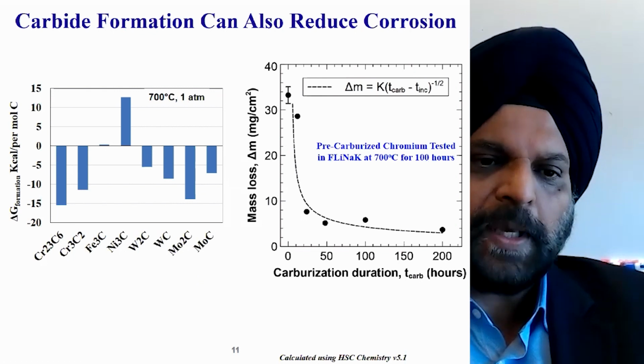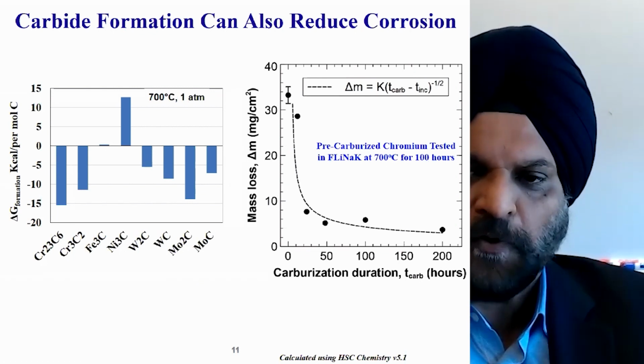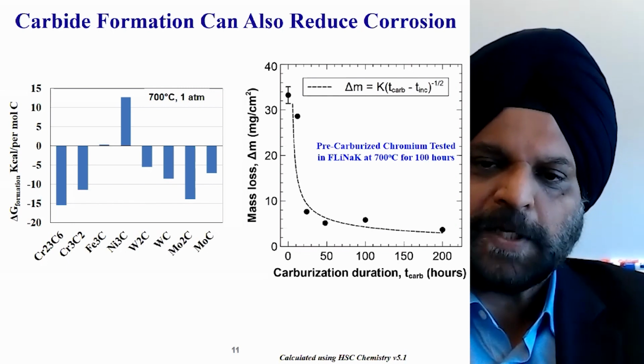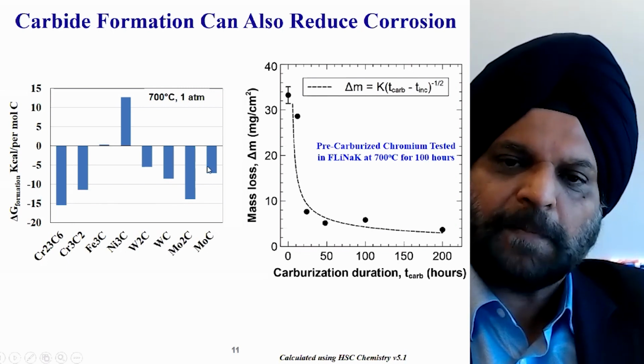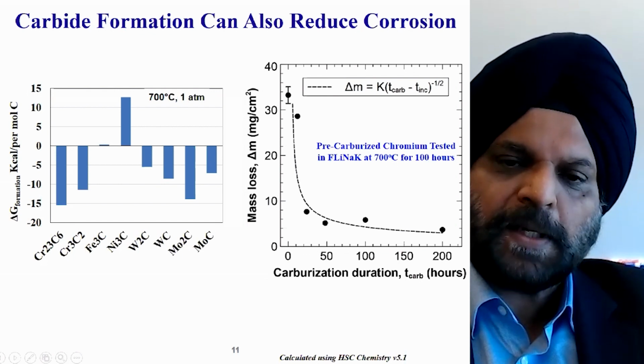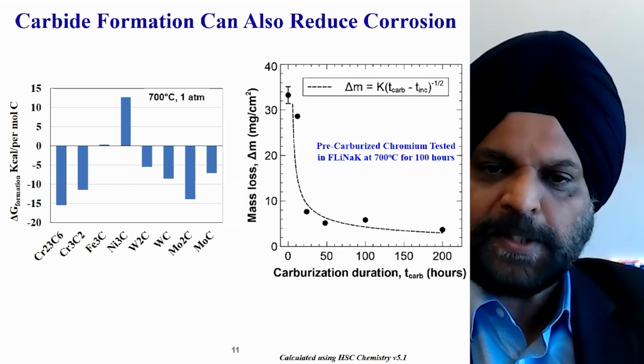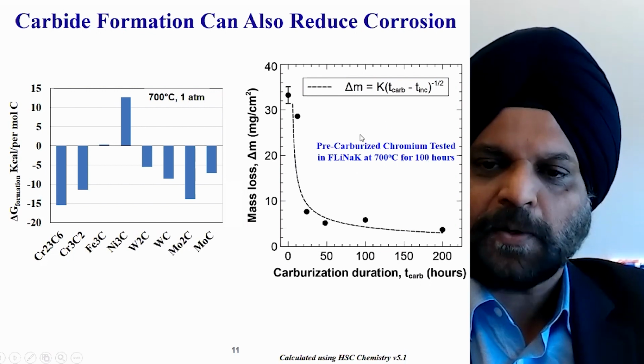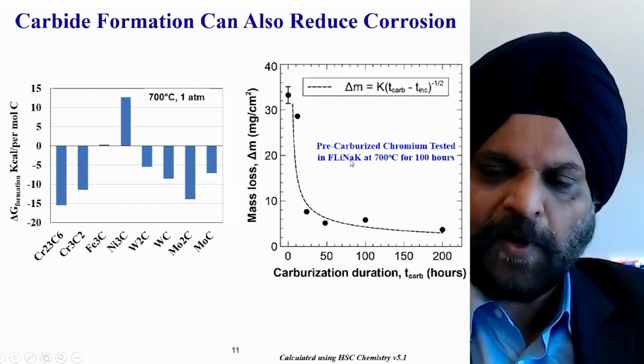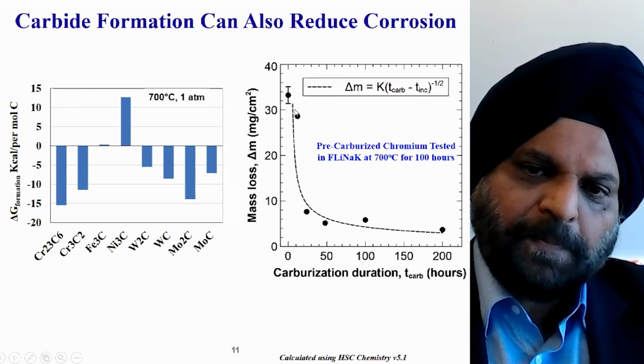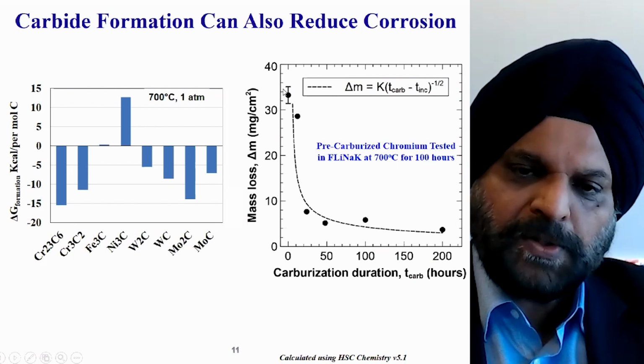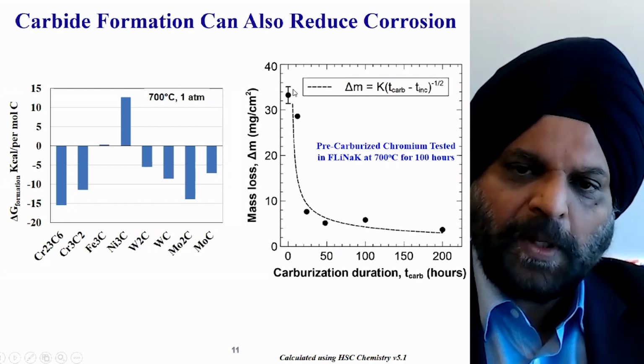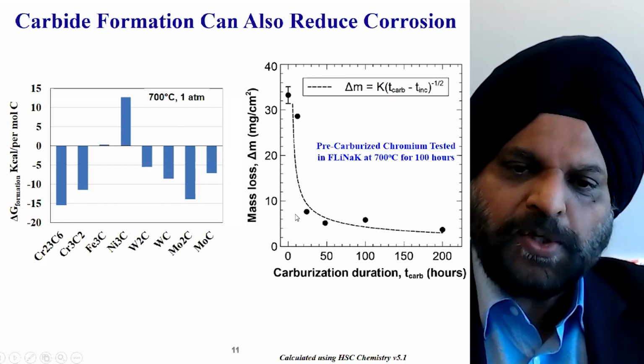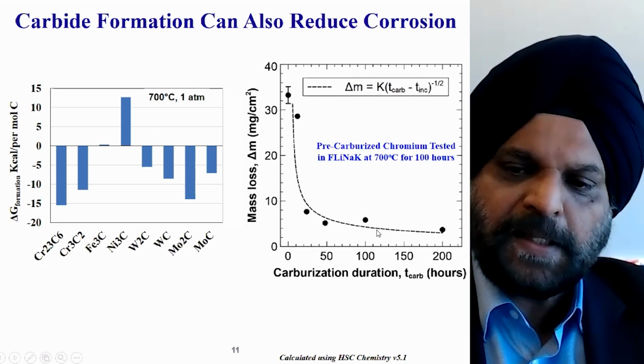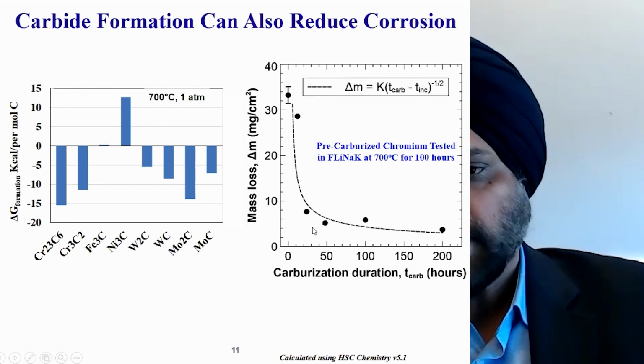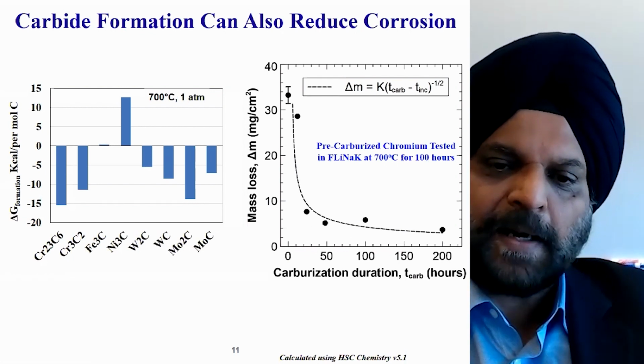We took chromium, we actually carburized it in gaseous form using a propane and hydrogen mixture. And we carburized for different time periods and used that carburized or chromium carbide layered chromium sample to test for its corrosivity or corrosion tendency in FLiNaK at 700 degrees Celsius. This sample here is for when there is no carbide on the surface. As we increase carburization, corrosion rate measured in terms of mass loss decreases significantly, which basically shows that chromium carbide is acting as a barrier layer.